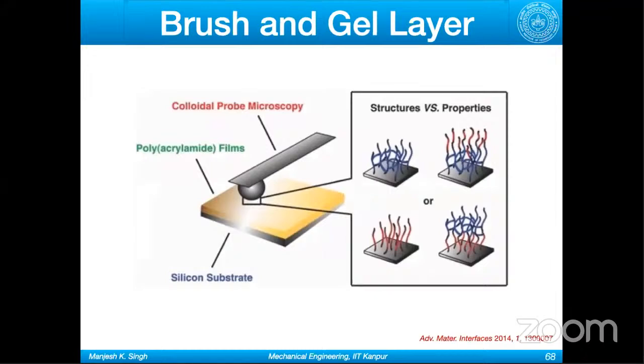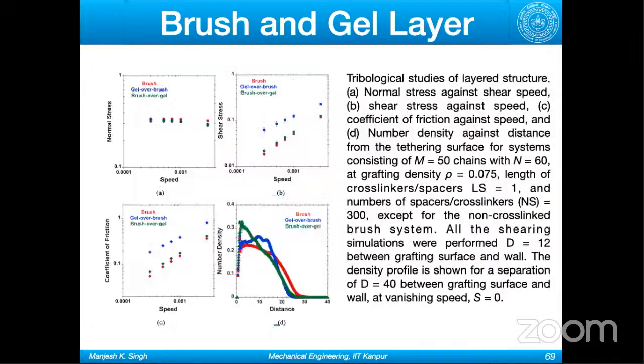And then there are brush and gel structures. As I was saying, gels are stiffer, with higher modulus, so they give you lower wear, but simple polymer brushes give you lower friction. So you can have the best of both worlds. You can have gels on the bottom and brushes on the top. So you will have less wear, and because the top layer has brushes, you have lower friction. And these are my simulation results again.